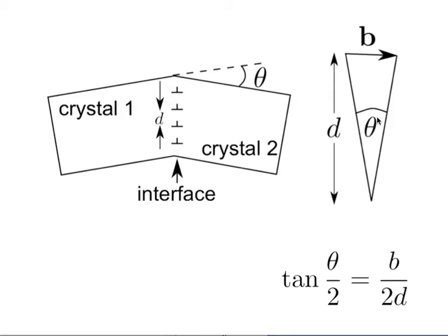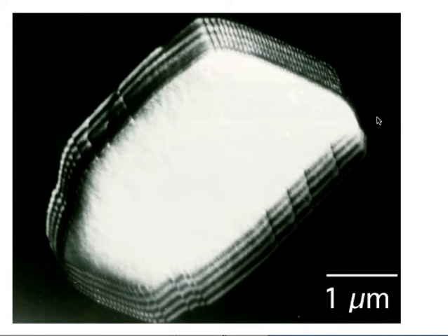You mentioned when I asked the question that you will see contrast from the interface, right? The contrast comes from the strain fields of the dislocations. If we look at a transmission electron micrograph, if you look very carefully, you can see lines here. Can you see that? Those are arrays of dislocations. This is what we call a weak beam image, where we have lit up only that crystal and the rest of the matrix is not visible. You can see arrays of dislocations here. That is the structure of the interface. That is what you see.